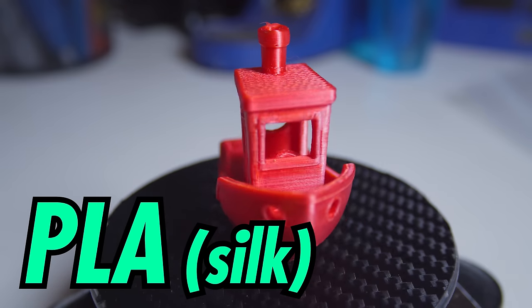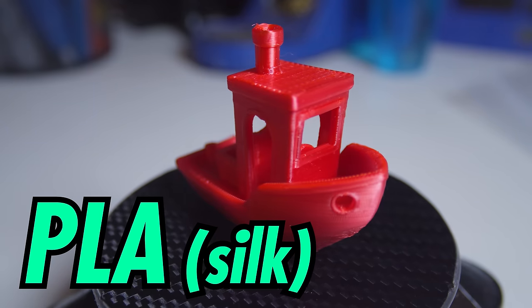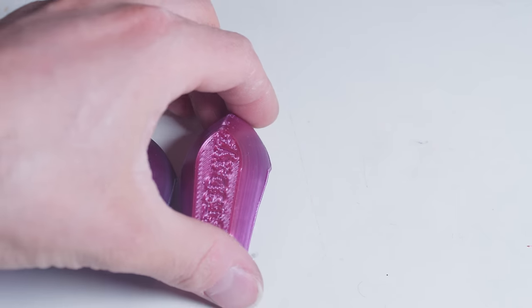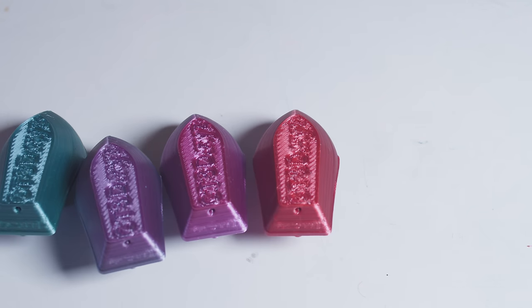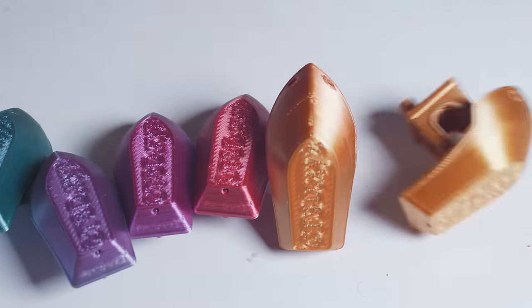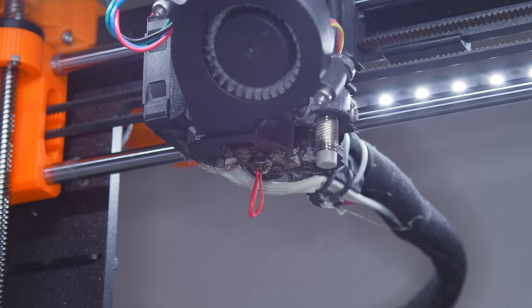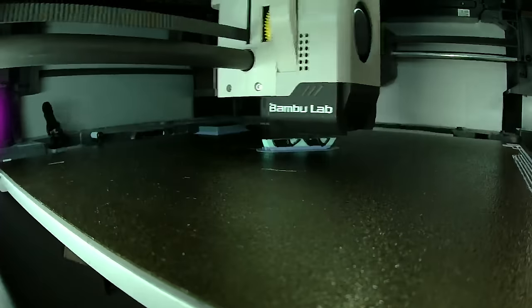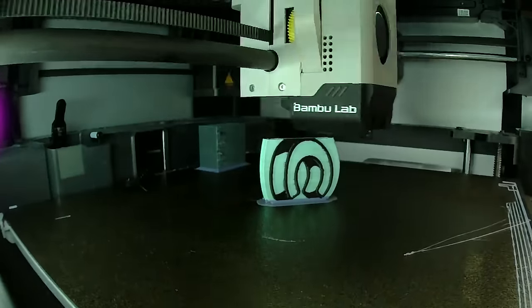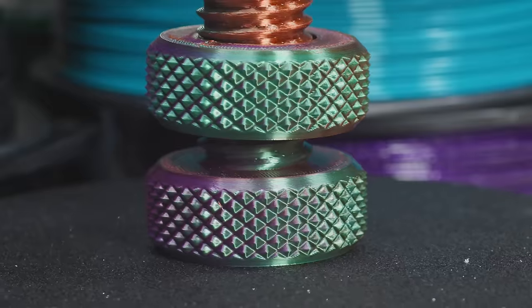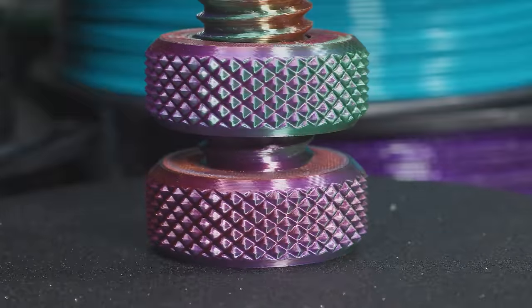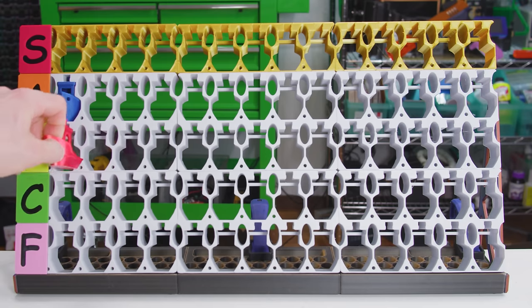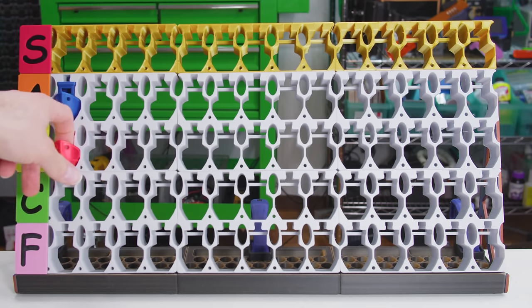Silk PLA has a special additive that makes your prints cartoonishly shiny. This stuff is more metallic than actual metal. This weakens the print, but it makes supports a lot easier to remove. And since Silk PLA literally shines in showpieces, I think this is a fair trade. But just keep an eye on your printer. When Silk PLA heats up, it puffs up like popcorn. So if your extruder fan is sucking hot air, or you're doing multi-material single-nozzle prints, Silk PLA can easily give your extruder a monster mamma jam. Silk PLA sacrifices performance for aesthetics. But in its defense, those aesthetics are really aesthetic. Because Silk PLA will absolutely trash both a Bambu AMS and a Prusa MMU, I'm gonna put it in B-tier. B for bi- Prusa and Bambu Lab, the two genders.